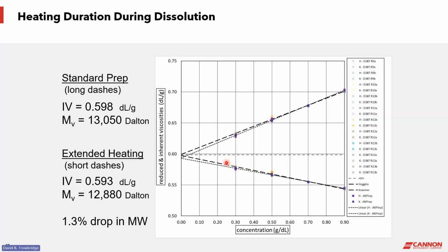Here's results of trying to determine if we're heating a sample too much during dissolution. It's an important consideration, sometimes hard to determine. So we dissolved a sample, and then we heated it for a little bit longer and measured the IV a second time. And here's the comparison. There's a 1.3% drop in molecular weight based on our analysis of intrinsic viscosity, which doesn't seem like much, but graphically, when you look at the Huggins-Kraemer extrapolations, you can visualize that there is, in fact, some indication that's fairly believable that even a short additional amount of heating is going to cause some degradation that you should be aware of.